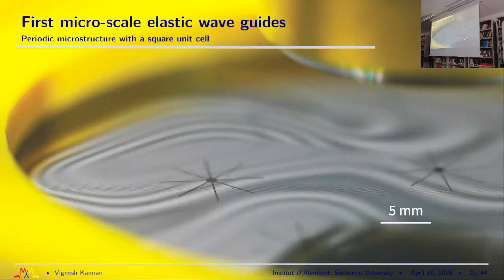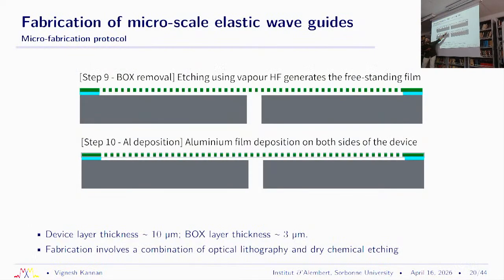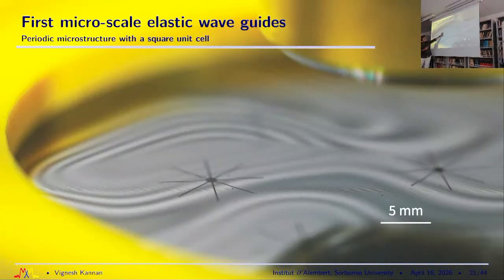Okay. So what I'm showing you here in the background is our first device. I'll tell you what this yellow thing is in a second. So what you see as a slight curvature is basically because of a little bit of thermal warping of our device layer. These stars that you see is actually the window on the back surface, and the reason we're doing this is you'll see in a second. And what you're going to see here is you'll have unit cells that are 10 micrometer beams, 100 micrometer unit cell dimensions, and so we have something like 600,000 unit cells inside a 100 millimeter wafer or a 80 millimeter region of a 100 millimeter silicon wafer, right?